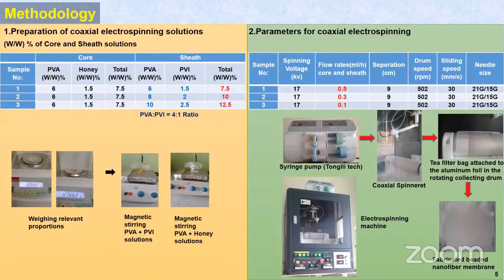For the preparation of solutions for coaxial electrospinning, we had to mix the solutions according to our unique design of weighted proportions. Weight over weight percentages of the two solutions can be seen in the left-hand side table, where the weight percentage of core solution is kept constant, while increasing the weight percentage of sheath solution, keeping the ratio PVA to povidone as 4:1. These are the steps followed for the preparation of core and sheath solutions. Initially, we had to weigh the relevant amounts, and after mixing them, we had to manually stir.